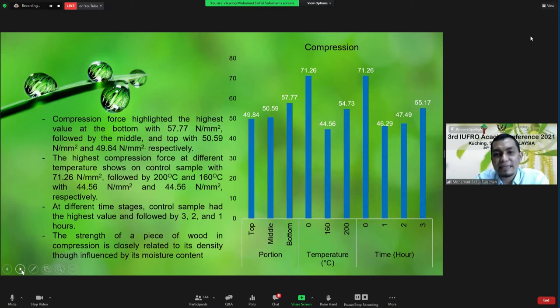This is slightly similar to static bending, as previous researchers believe compression strain value generally deteriorates with increases in temperature or exposure time. The reduction in the strength of the heat-treated samples can be explained by the progressive degradation of the hemicellulose between the microfibrils in the sample itself.